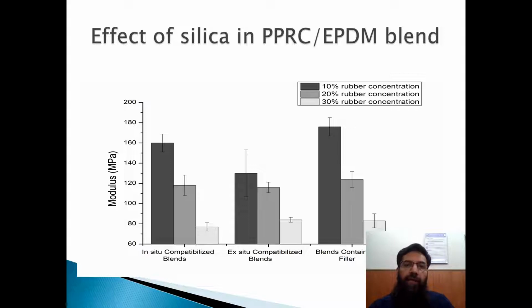So if we take the examples of the different other compounds, just like the PPRC, EPDM blends, and if we look at the properties, the compounds which are having silica as a filler show you the better modulus. Just like you can see here, the compound having the 10 pHr of the rubber content in the PPRC and silica up to 5% loading gives us the better performance as compared to the non-reinforced compound having no loading of the silica. Similarly, with the increase in the rubber content, a similar trend we get, the modulus increases as we incorporate the silica as the nanofiller in our compound.